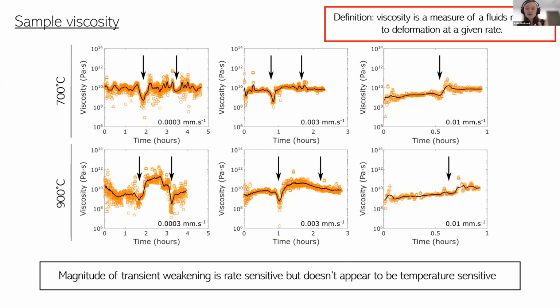So I should say that all of these ones we've gone through the transition twice, but because we're wanting to understand the microstructures at the point of the transition, we quenched loads of samples midway through the quartz to coesite transition, so through this first transition that you can see with the black arrow. And the first type of microscopy that we use is microcomputed tomography, or micro CT. And this is a non-destructive process.